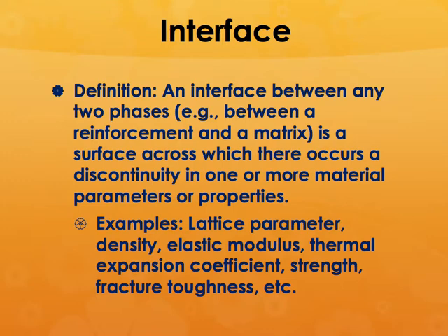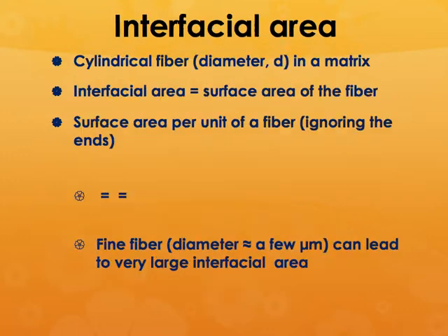And it is going to control multiple properties of the composite. Mainly it can control the elastic modulus, thermal expansion coefficient, strength, and fracture toughness. Others are there, but the effect of the interface is not as strong as in the case of elastic modulus, strength, and fracture toughness.